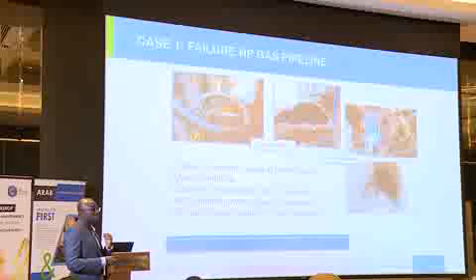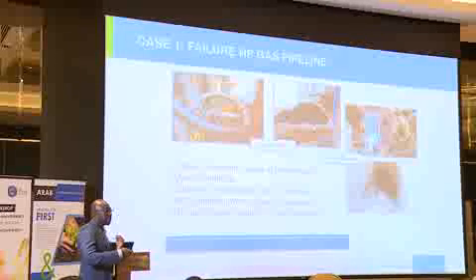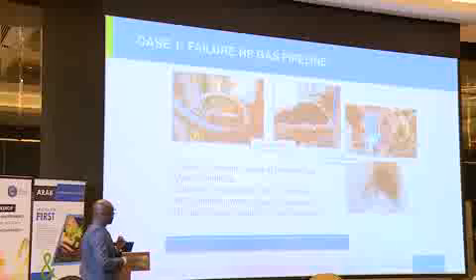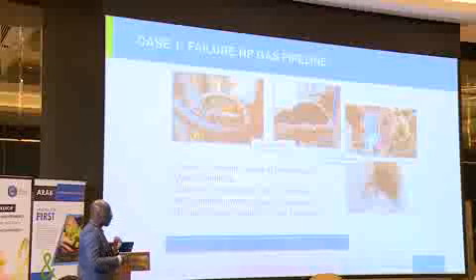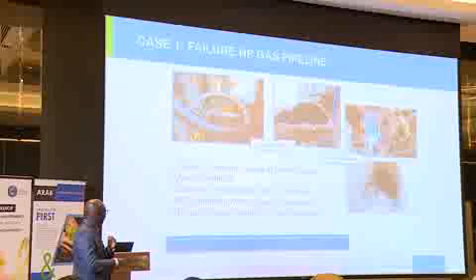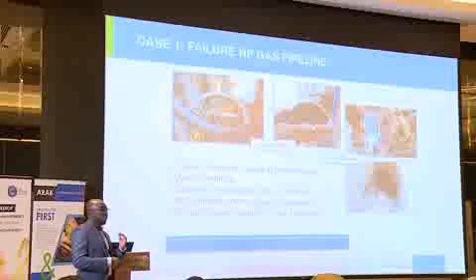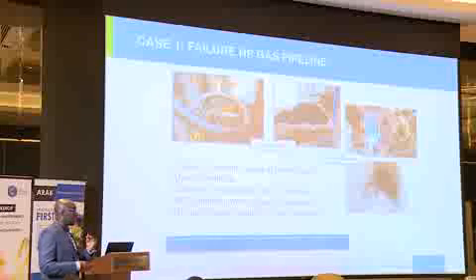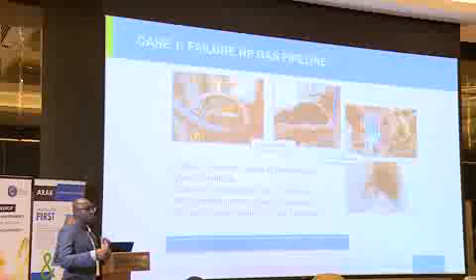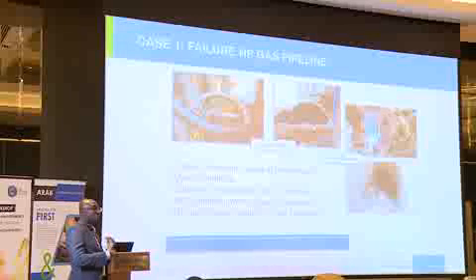the lesson here is that when you have upset conditions, you should incorporate this into your risk-based inspection system if you have one. Even if you do not have one and you have upset conditions where your piping is affected, you should try to figure out, one, what was the contamination product? Will it have any effect on the piping? And if it will, how can we further mitigate it? And if you have a running RBI system, this should be fed into the system to determine how it will affect the risk ranking of the pipeline or particular set of pipelines that have been affected.